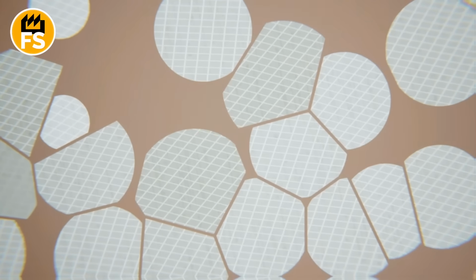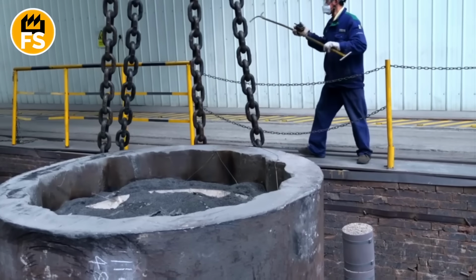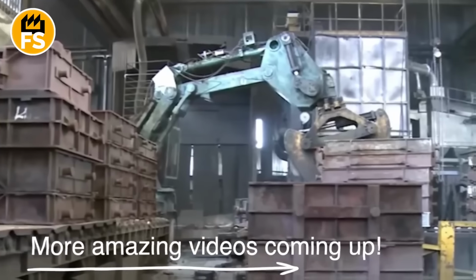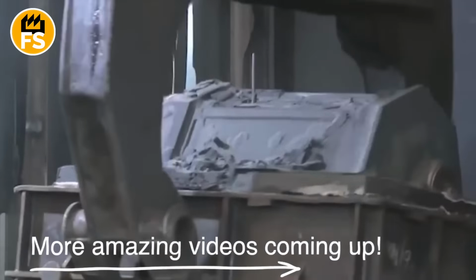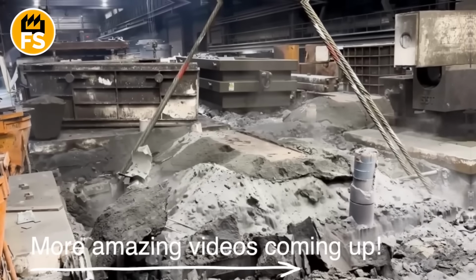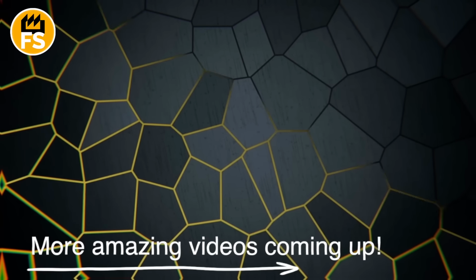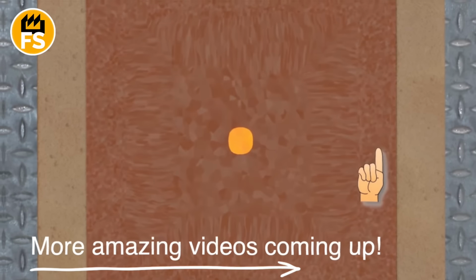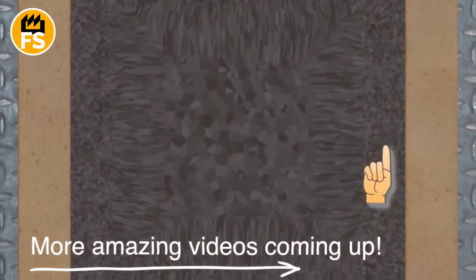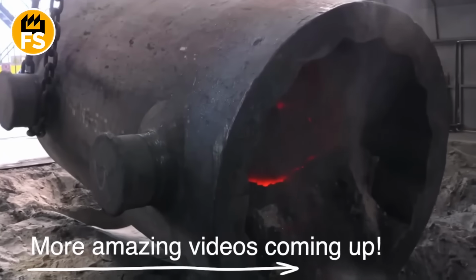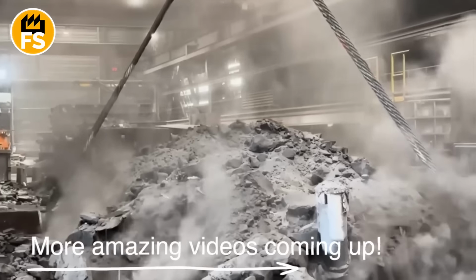To ensure uniformity of the crystalline structure, the 607-ton ingot was left to cool in the casting pit for 6 weeks. This is a controlled, incredibly slow process, during which the steel gradually solidifies, dropping to a temperature of around 2000 degrees. This slow crystallization allows the metal to avoid unwanted phase transformations and guarantees a high-quality macrostructure, which is the key to the strength of the future component. Only after this lengthy solidification period is complete, the steel monolith, which after shrinkage and removal of the defective top portion weighs approximately 320 tons, is carefully extracted from the ground.